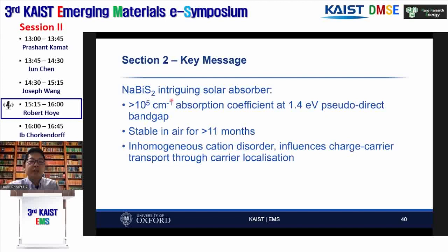optical absorption coefficients with quite an ideal band gap for solar energy harvesting. It's very stable in air, very stable for over 11 months. And it has this property called cation disorder, which can lead to localized sulfur p states that then strongly influence charge carrier transport through carrier localization. And this emphasizes that carrier localization is an important property that more people should be investigating in the early stage exploration of novel solar absorbers. So I just wanted to summarize my talk.